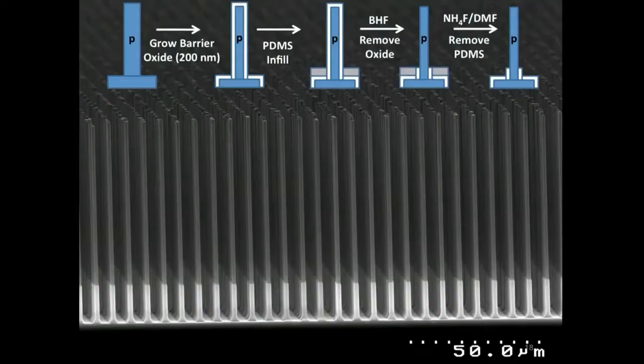The way we do that here is we thin that polymer, and we use it as an etch stop. After fully oxidizing those rods, we then cast that PDMS to thickness like this. We etch the rest of those rods that are oxide coated to reveal them except at the base, and then we make a diffusion just with spin-on glass to make a radial electrical junction. It's an N-type radial sleeve on top of these P-type doped base systems.